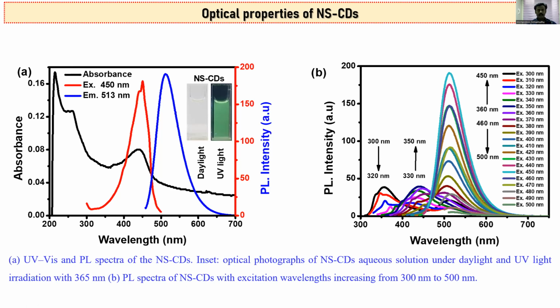Moreover, the excitation band at 440 nanometer is related to the n to pi star transition of the carbonyl bond, which is affected by the surface nitrogen and sulfur in the carbon dots. The carbon dot solution was basically colorless in daylight, but under UV light radiation, it turns bright green under a 365 nanometer UV lamp.